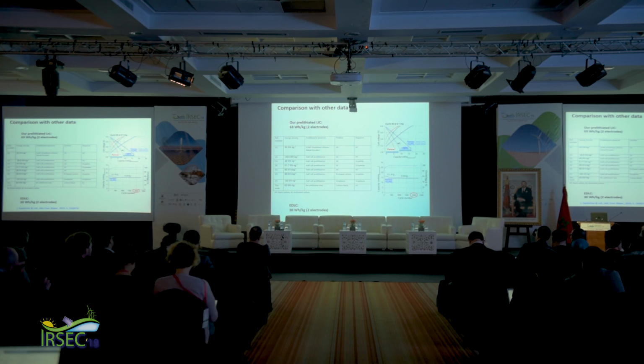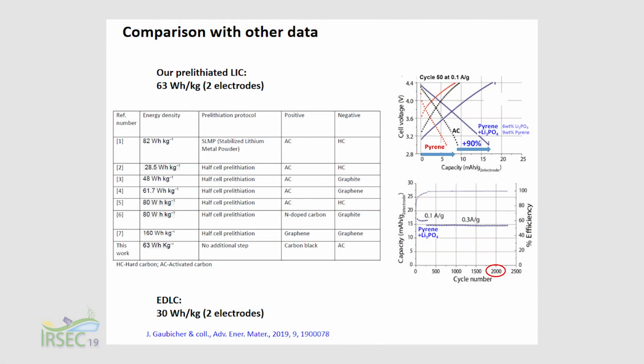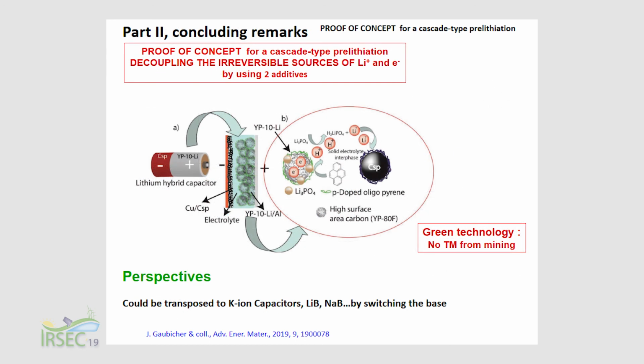Okay, so to compare our results with other data, we obtain an energy of 63 watt-hour per kilogram of the two electrodes, and we compare with other data in the literature, and you can see that we are in the same range. And to conclude this second part of my talk, I will say that we have proposed a new concept for pre-lithiation that uses two irreversible sources for lithium ions and electrons. And this technology is green. It doesn't use any transition metal. So that's interesting.